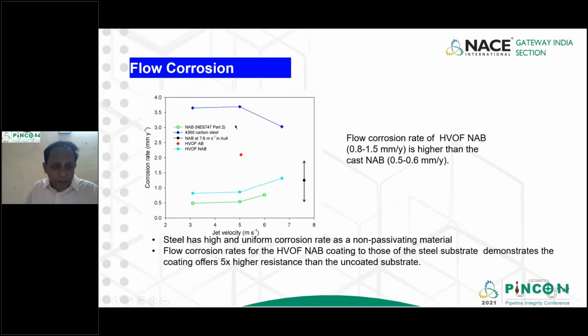What happened here is called a flow corrosion experiment. There was no sand particle; I just want to talk about this. If you look at the x-axis, the velocity, I looked into the corrosion rate. Now I did the cast NAB, this green color. You could see that the cast NAB was behaving better than your bare substrate, the base 4360 carbon steel. Then also if I compared with NAB.